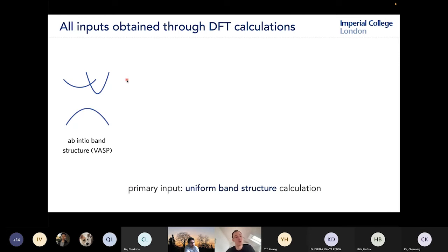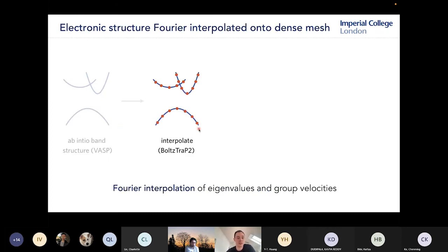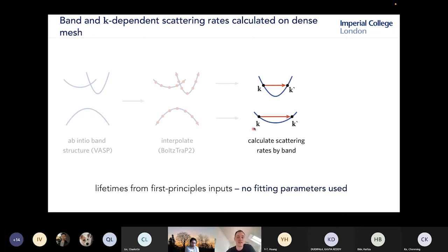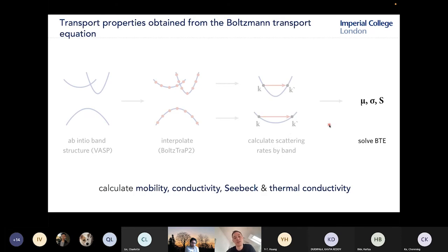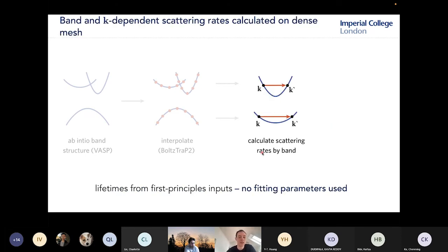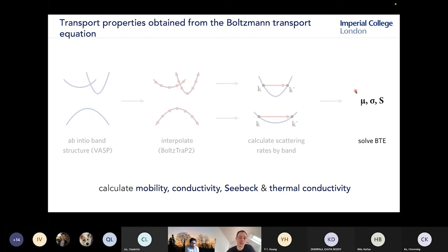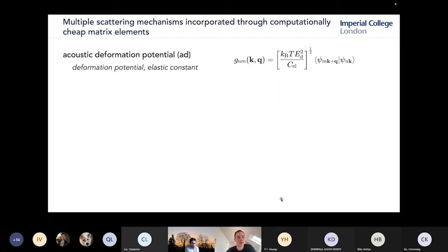The way this works is we take an ab initio band structure, and all the calculations that I'm presenting were calculated using the Vienna Ab initio Simulation Package. We take a band structure calculated using DFT, interpolate it using Fourier interpolation, and calculate the k-point dependent scattering rates. I'll go into this in a little more detail in a second, but the gist is that there are no fitting parameters used here. Everything that goes into this calculation is obtained from first principles. Then we solve the Boltzmann transport equation to get transport properties: conductivity, mobility, Seebeck, and thermal conductivity. The trick in AMSET is that we're using computationally cheap matrix elements that rely only on common materials parameters. So there's a range of scattering mechanisms that we can model.